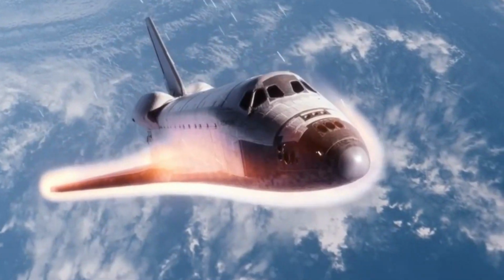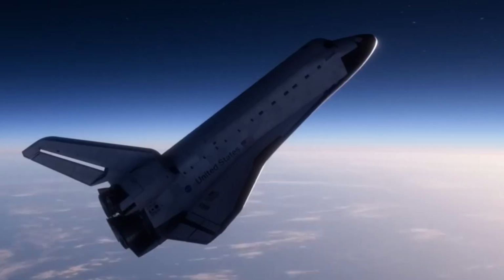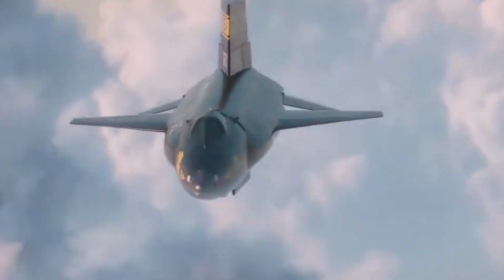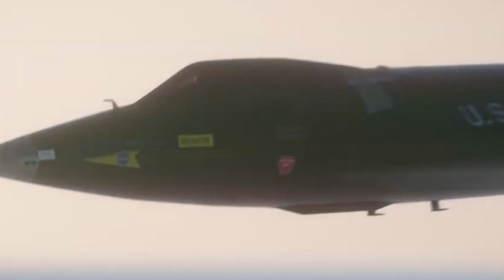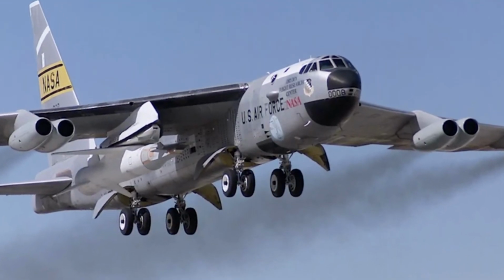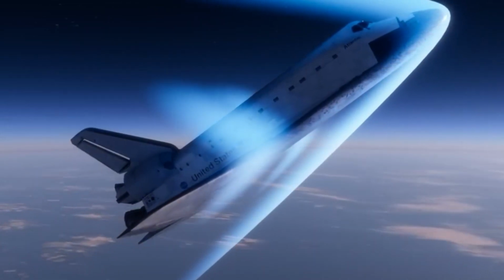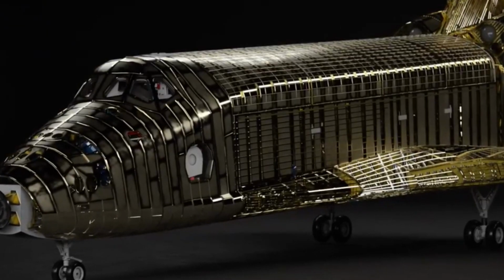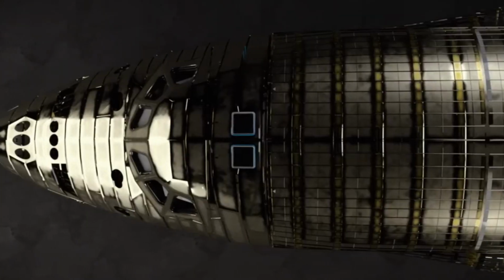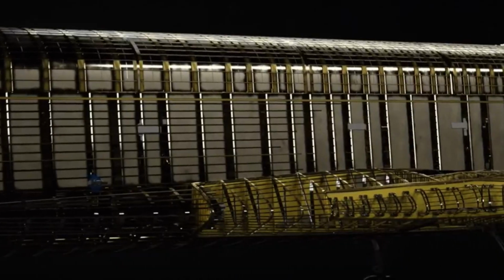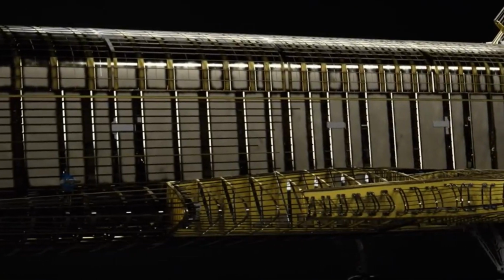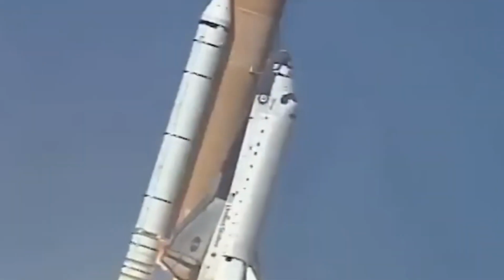The leading edge of the orbiter's wings is composed of 22 of these carbon-carbon panels, with sealing strips covering expansion gaps between each panel, an essential solution to a lesson hard won during the development of the X-15. To investigate the heat of hypersonic flight, the X-15 was painted with a special kind of paint that reacts to heat. After one flight, the X-15 returned with strange wedge-shaped patterns emanating from the leading edge expansion joints. These small gaps in the leading edge allowed the superheated plasma to flow inside the aircraft structure, rapidly causing erosion and melting. These findings resulted in the sealed design we see on the space shuttle.